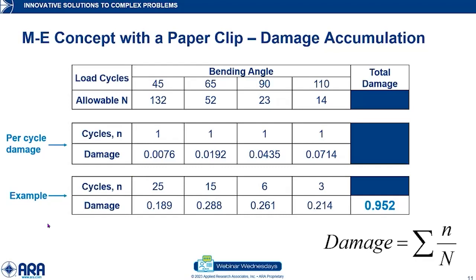So for each angle you bend it at, for 25 cycles at 45 degrees, your damage accumulation is going to be 0.189. So the idea is, when you reach one, theoretically, a total damage of one, that's the point that's going to fail. This basically employs Miner's hypothesis, which is the most common damage accumulation model around. It's used for a lot of things, not just paper clips and pavements, but other materials as well. It's not totally absolutely correct, but it's good enough. It holds up well enough to use.